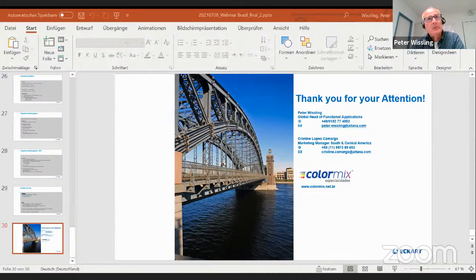In that case, we recommend this zinc paste, 10% mineral spirit in paste form. You can basically call it also a dedusted powder. This completely avoids any dust formation. Several companies have very high regulations for working safety in production, and this includes avoiding any dust formation during the mixing and processing steps. So in that case, we would recommend zinc flake paste, ProFlake paste, but it is a safety aspect.